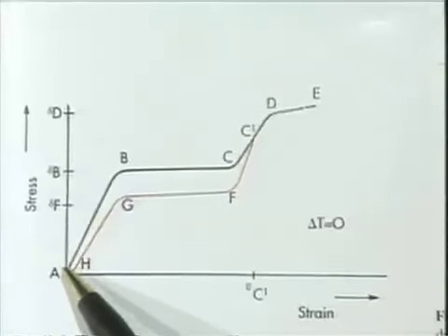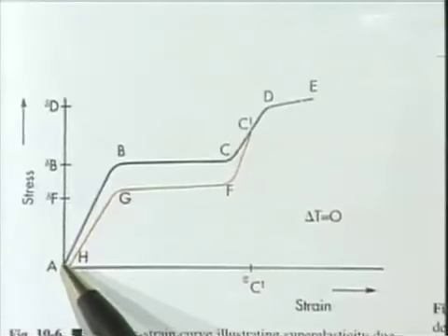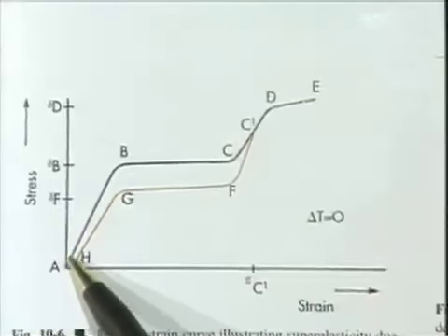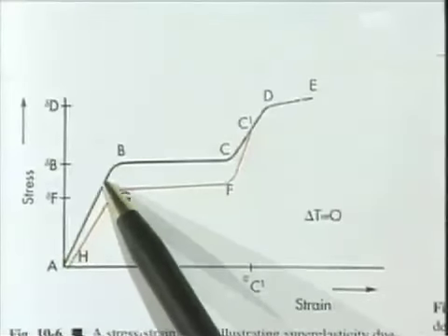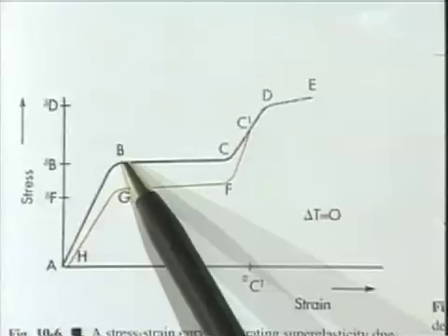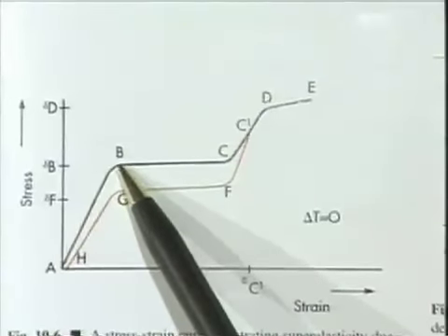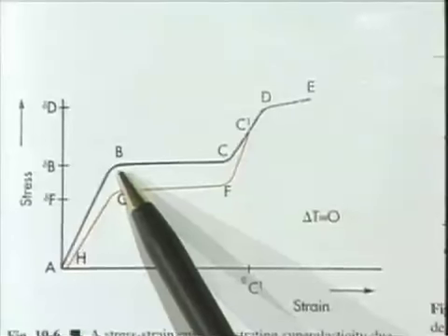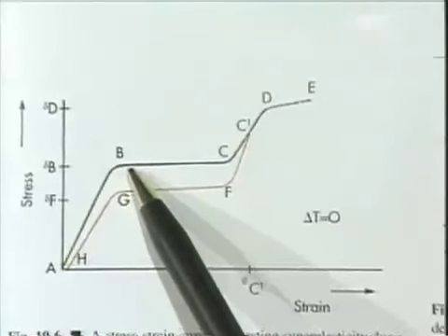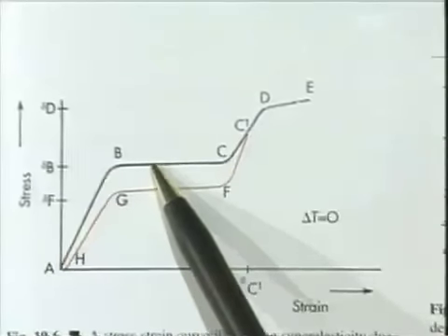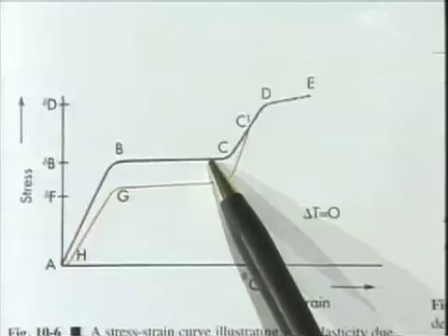Let's imagine that we take a piece of superelastic wire. It's supplied in the austenite form, and it's relatively stiff initially. As we bend it, it has a linear portion, and then at a certain point we hit a shoulder. At this point, we begin to induce the formation of martensitic nickel titanium within the austenite. And as that phase transition occurs, the wire bends, but the force doesn't go up.